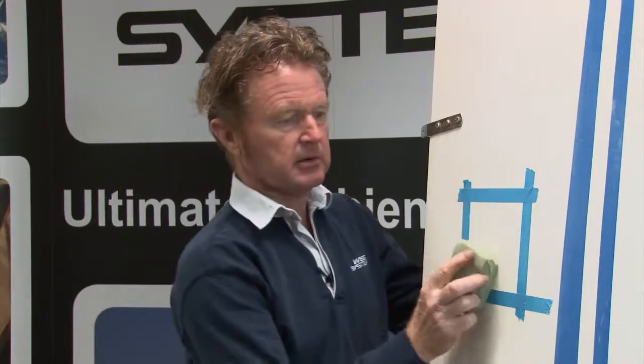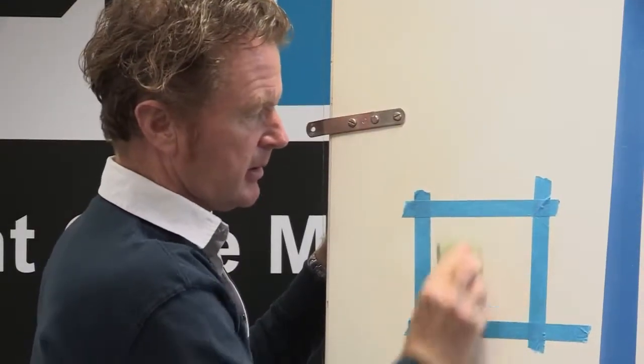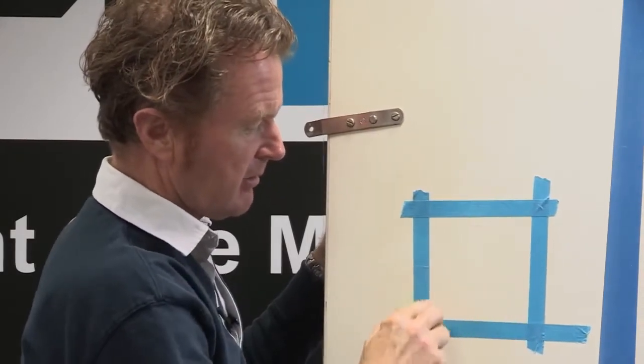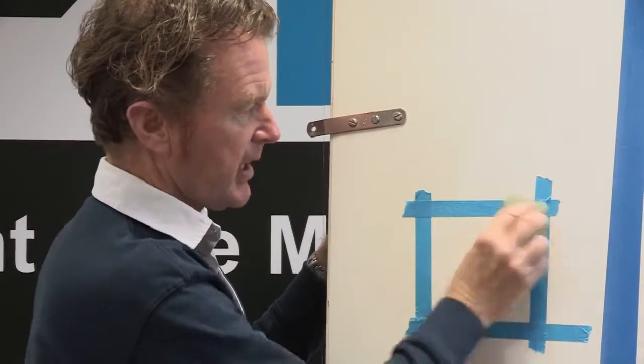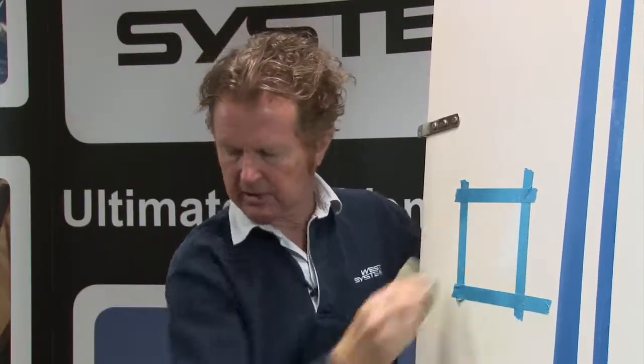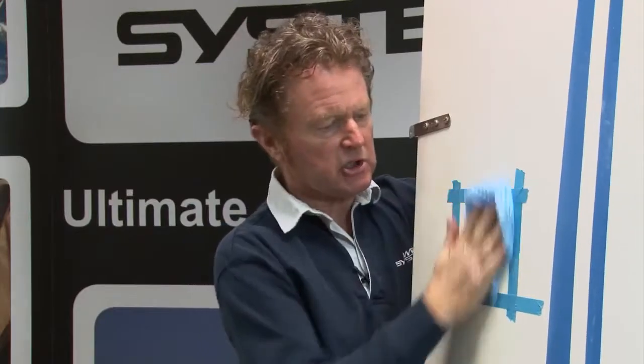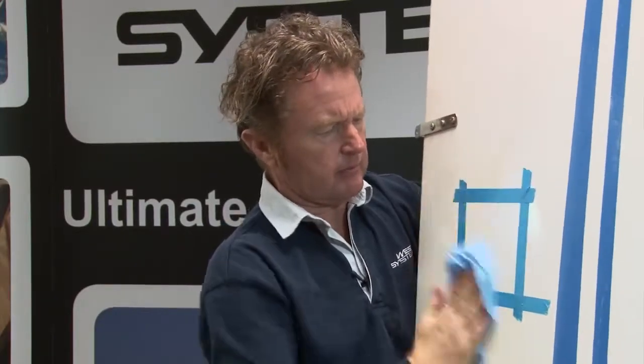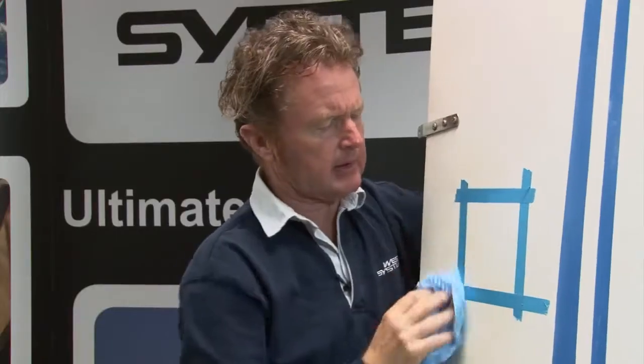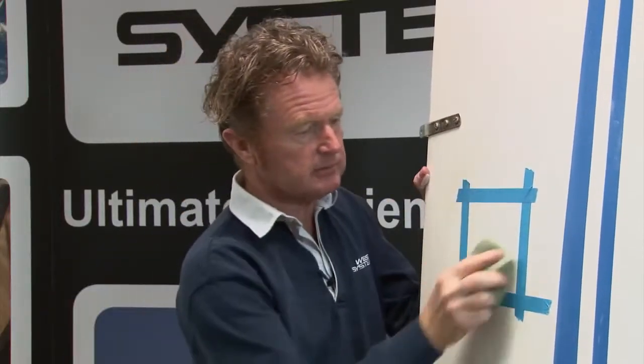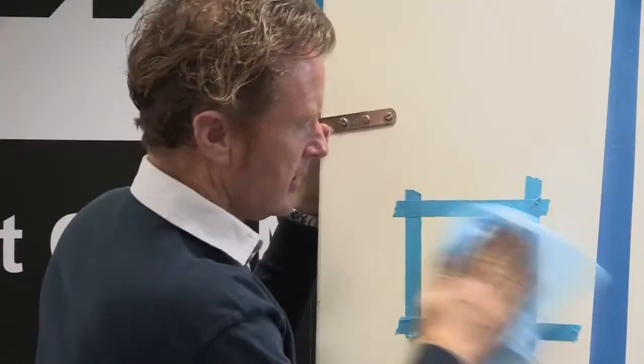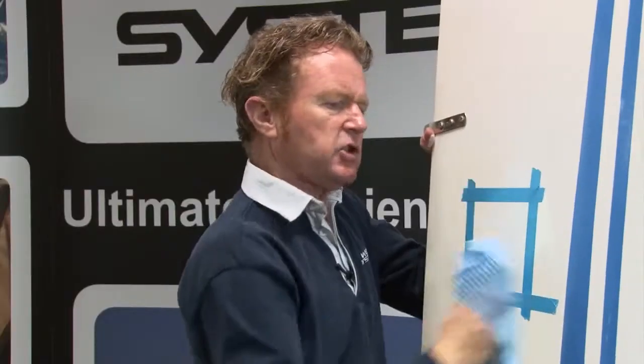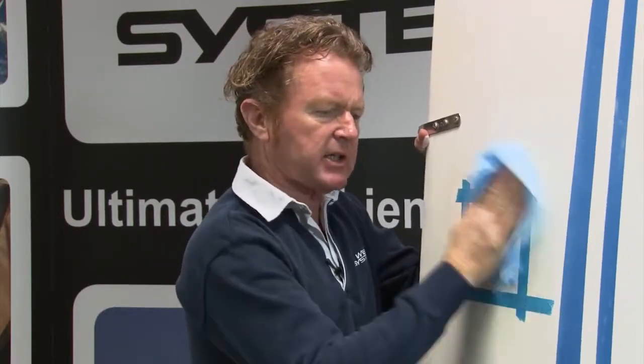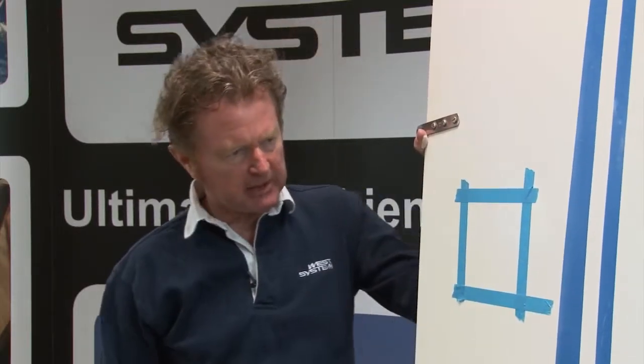And we apply that with a sponge, making sure that we cover the entire surface area, making sure the masking tape is well attached. Get plenty of wax on there, then use a clean cloth to burnish that up. Put another coat on. You generate a little bit of heat, it seals the wax and it creates a thin film of release wax upon which we can laminate our backing plate.